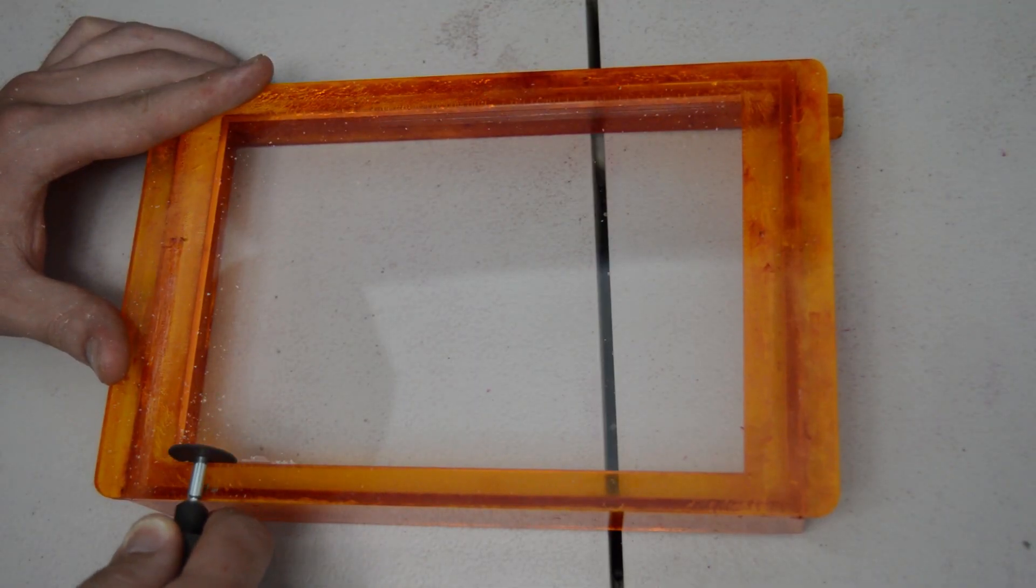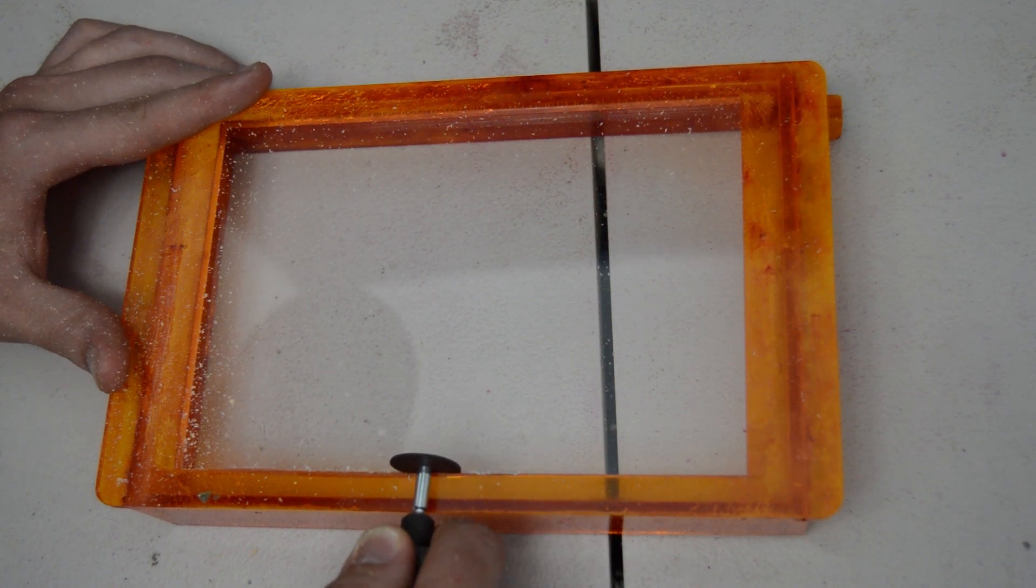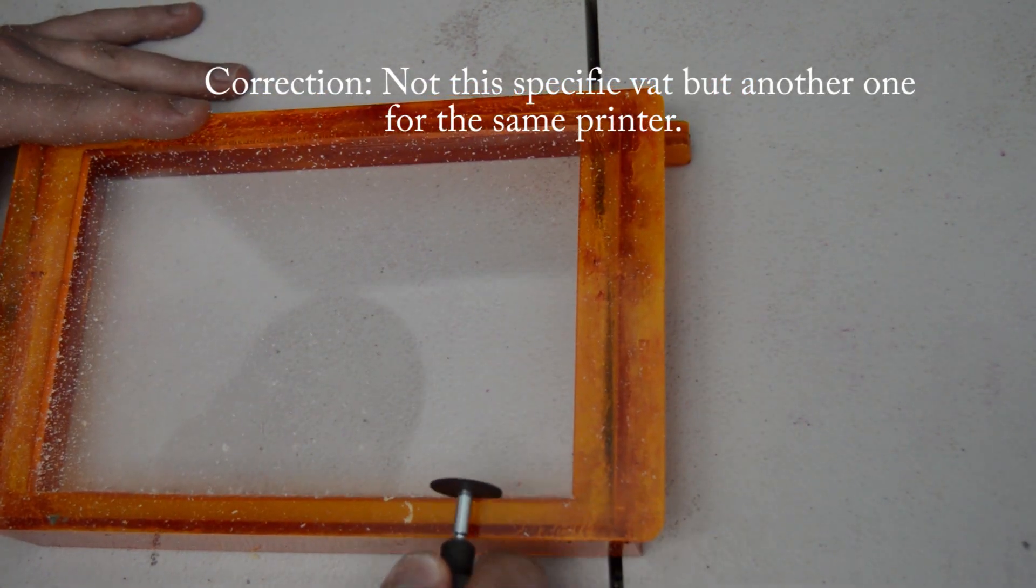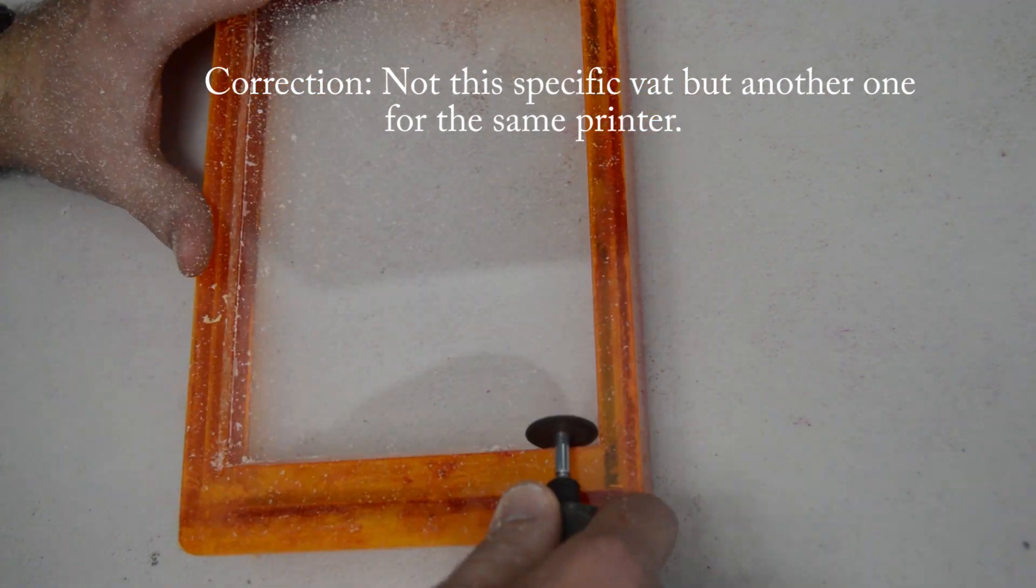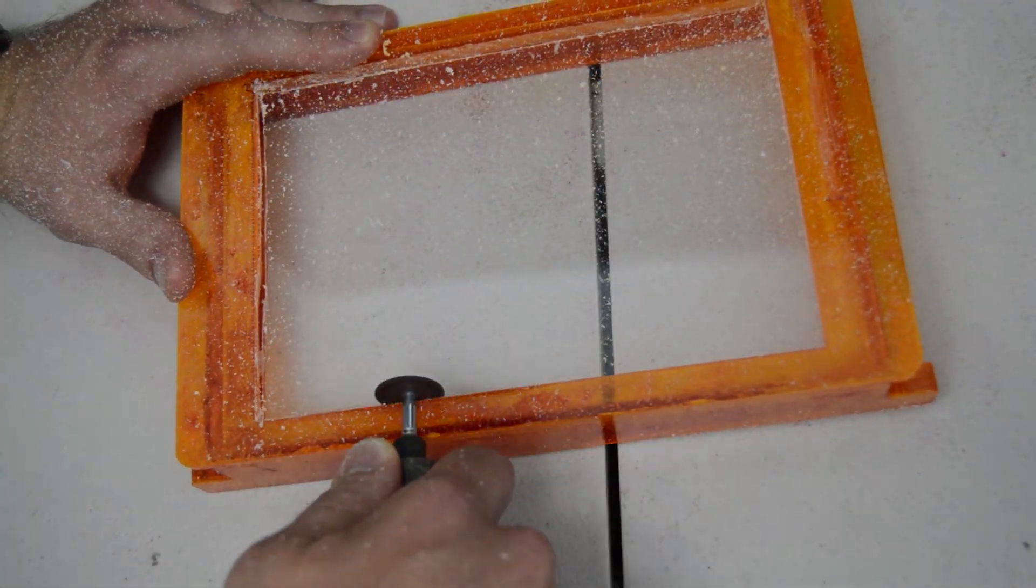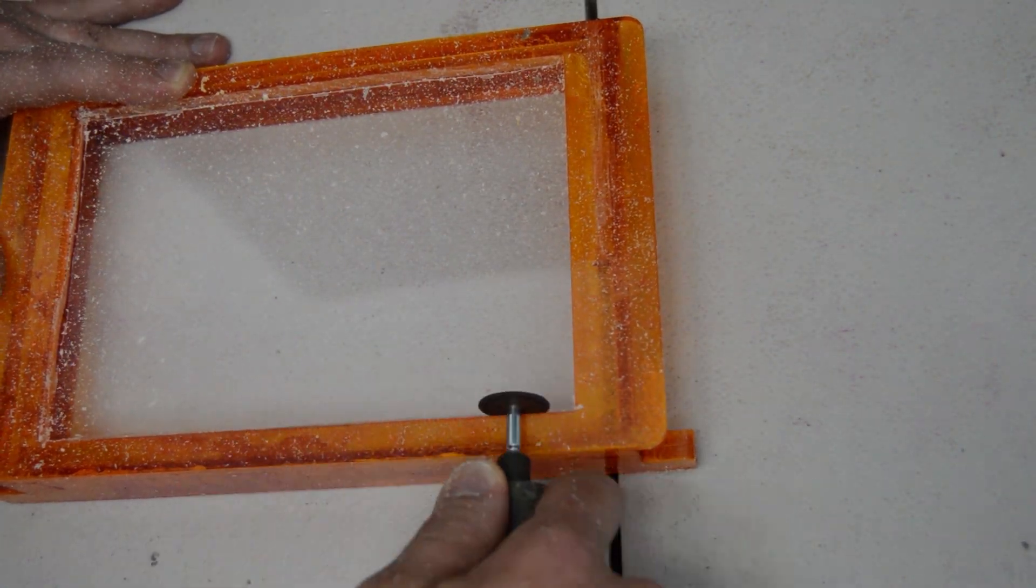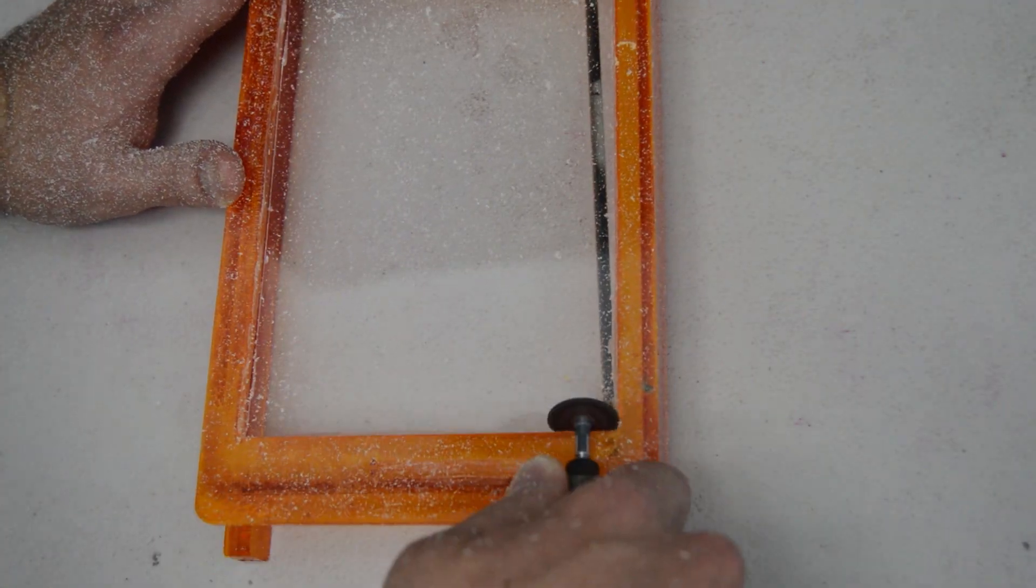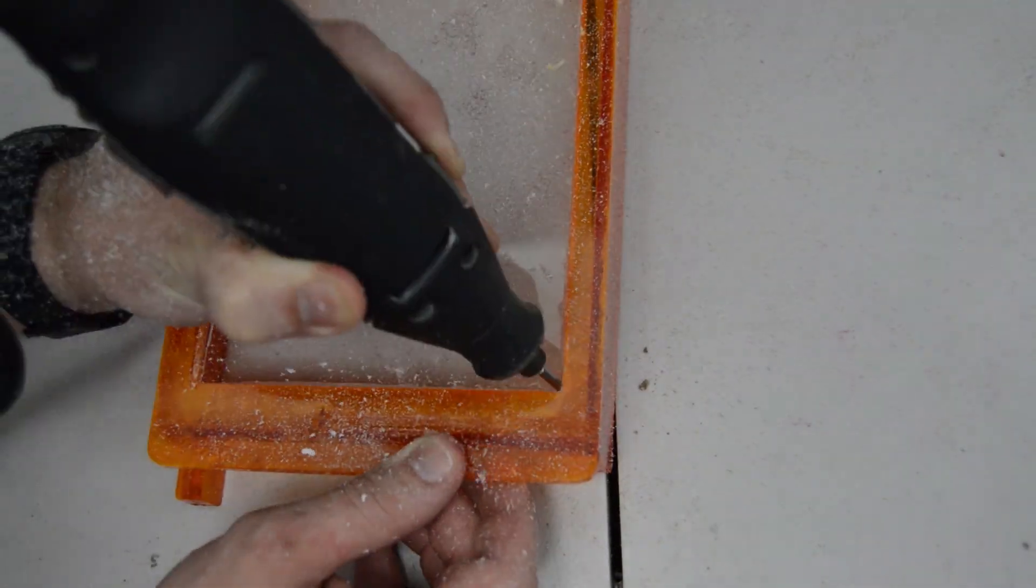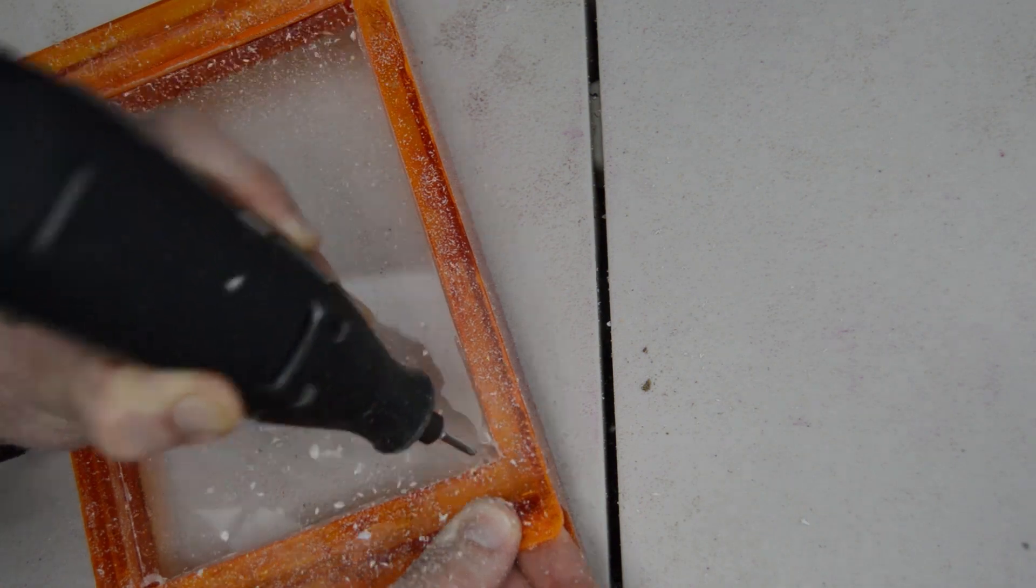Now for this vat, I will be modifying it somewhat before recoating it with PDMS. This is because at some point early in this vat's lifetime, I accidentally touched the acrylic window on the bottom with a little bit of Fun-to-Do deep black resin. This resin had a pretty negative reaction to the acrylic and caused crazing that started in the corner where it was touched and eventually spread across the whole window. I will be replacing the acrylic with glass to prevent this crazing from occurring in the future.